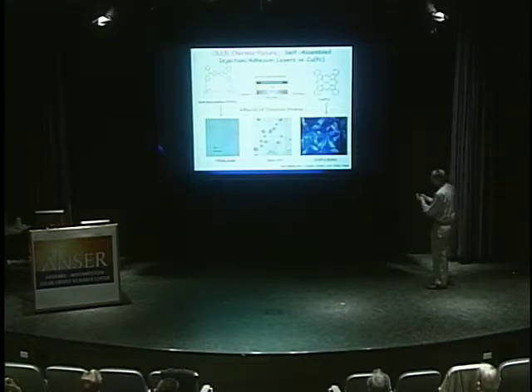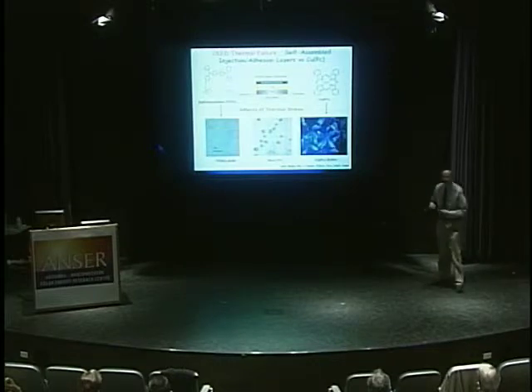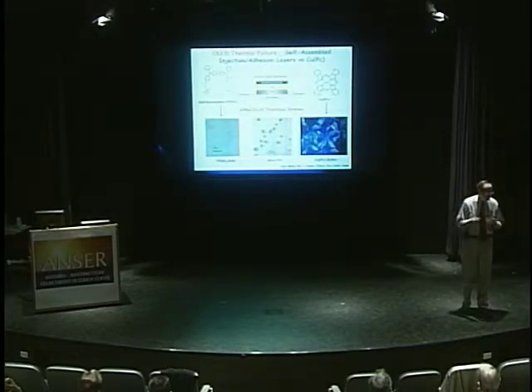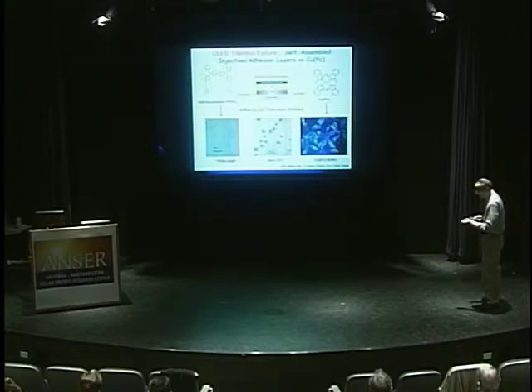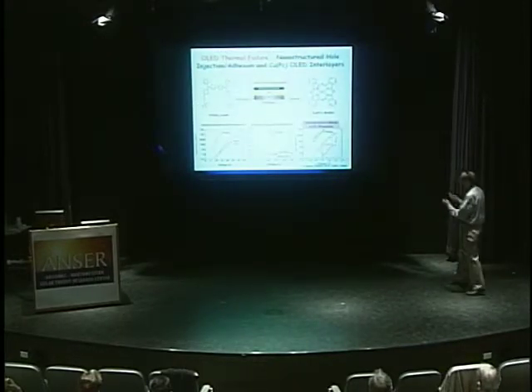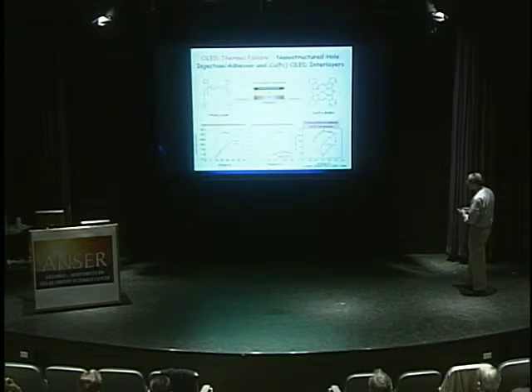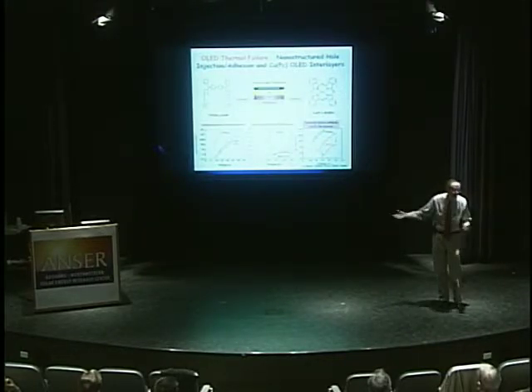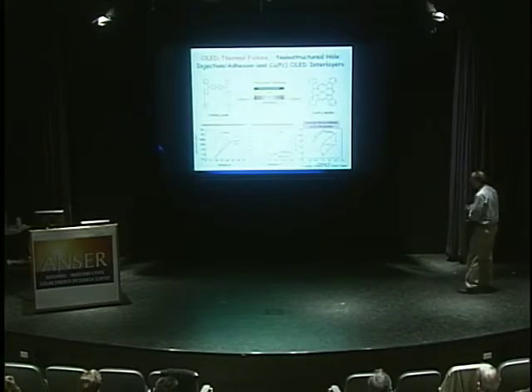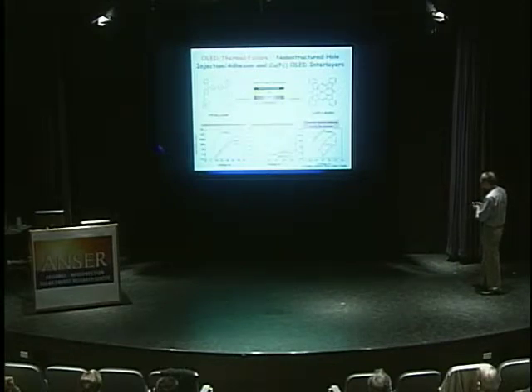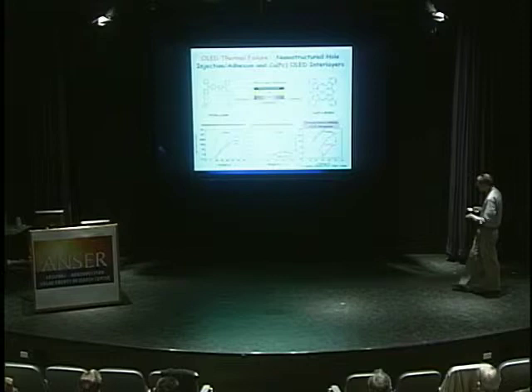What this student Ji Tsui did was he took the TPD architecture and fastened onto it 2 linkers so he could covalently link it, bind it to the ITO anode, to this oxide anode. And then you don't see any de-wetting at all. Ji made some devices. These are early devices from our lab, but the important thing is, in terms of electroluminescence, quantum efficiency, response to thermal stress, which meant Ji put it in the glassware oven for half an hour, you found a remarkable ruggedization of this multi-layer structure with just a few angstroms of this interlayer.